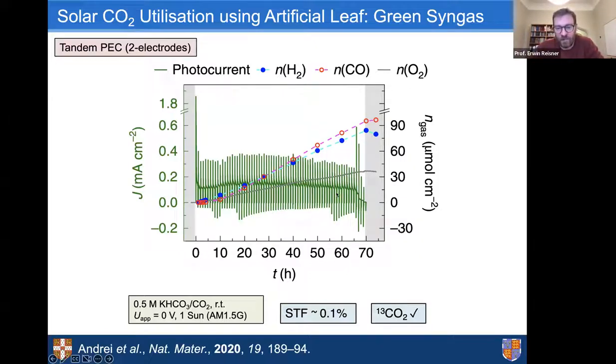The big disadvantage, I think those in the area will have spotted this already, is the current densities are low. So we're only looking at maybe 0.12 milliampere per square centimeter. And if you translate this to solar to fuel conversion efficiency, this is really taking all the energy in the solar spectrum and how much you have stored in the fuel. This is quite low and sits at about 0.1%. Okay, I think it's a start, we could show it works, but it does not work very efficiently.